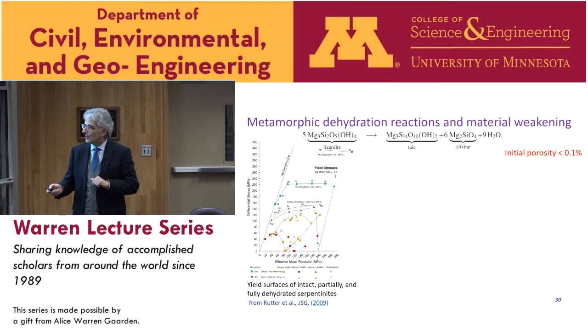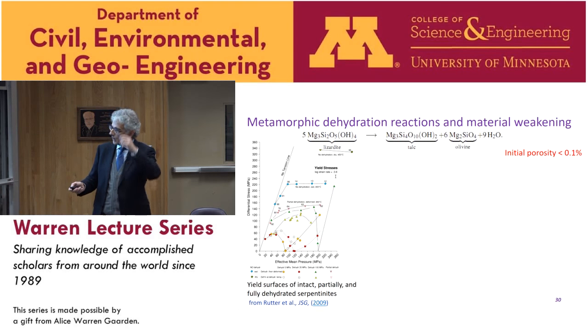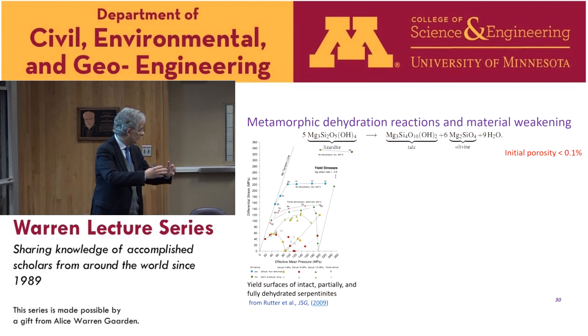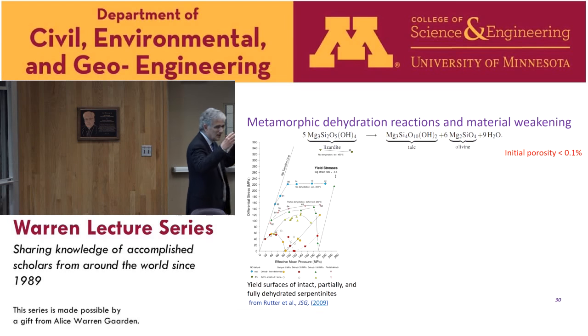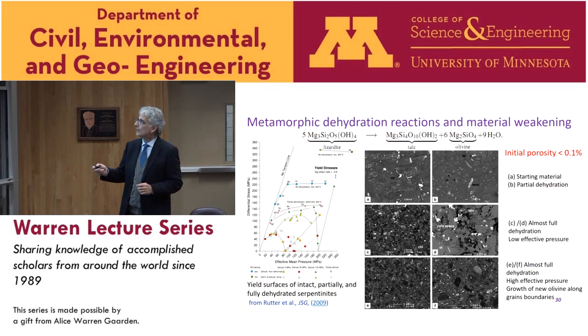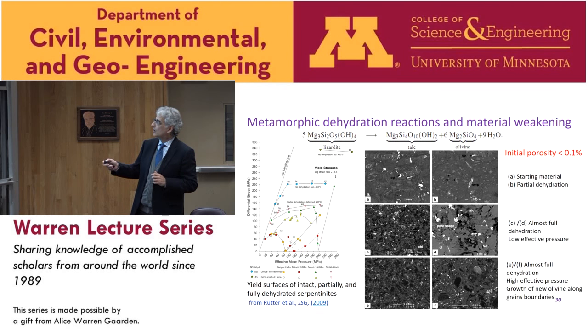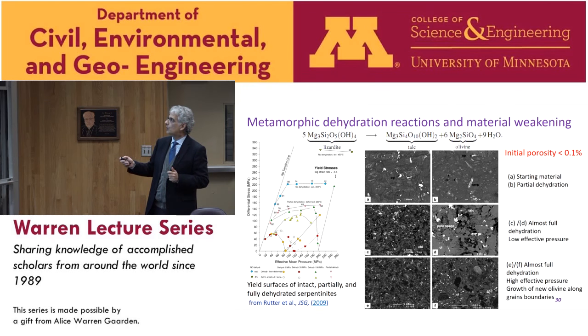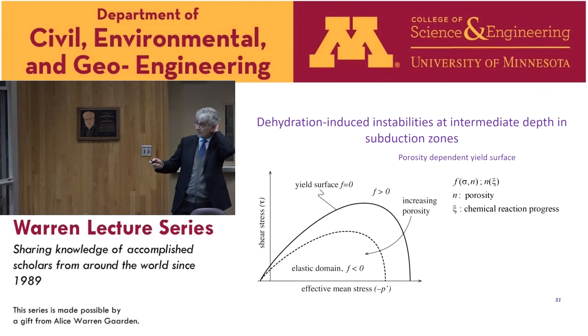For this, we take some experimental data published by Raleigh and Paterson on serpentinites at various degrees of dehydration. These are triaxial tests. So this is the non-dehydrated rock, and at various levels we see that the yield surface is shrinking. So it's like in porous rock, when we have a porosity-dependent yield surface, with increasing porosity, the yield surface is shrinking. And we see here from some micrographs given in this paper, starting from a porosity of almost 0, only 0.1%, the creation of porosity, and also we see big pores here, and also some new olivine nanograins along boundaries.